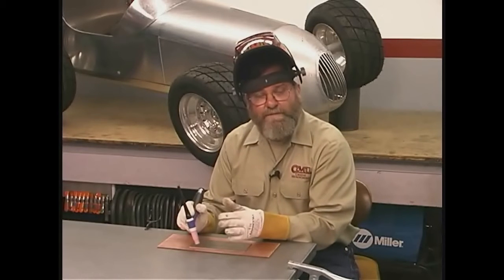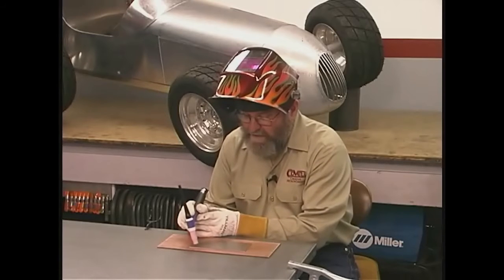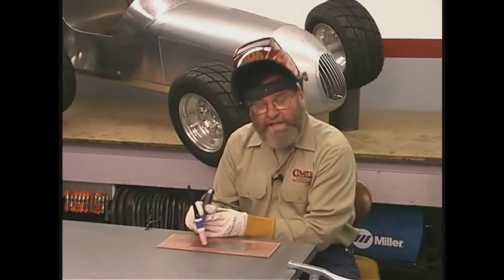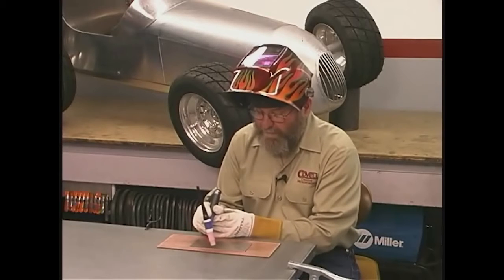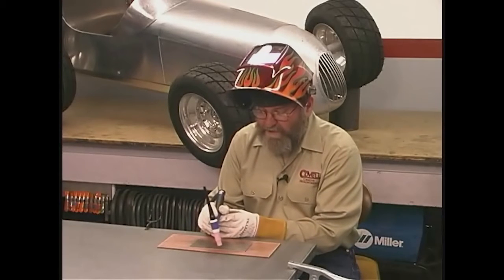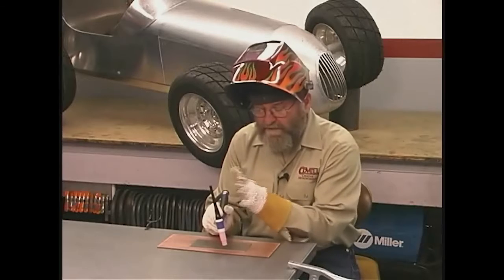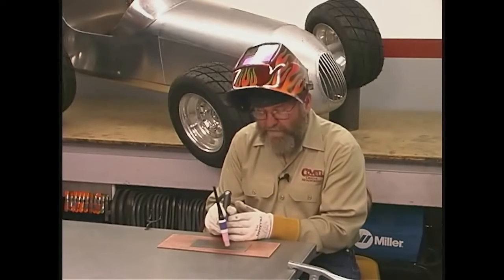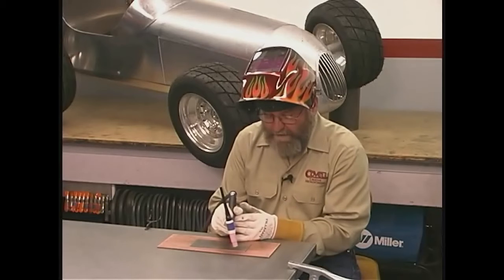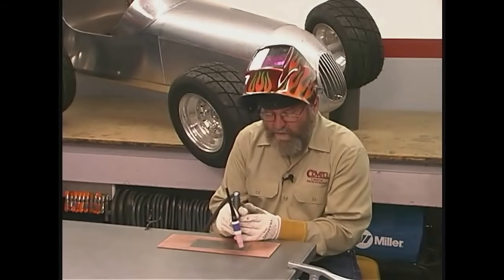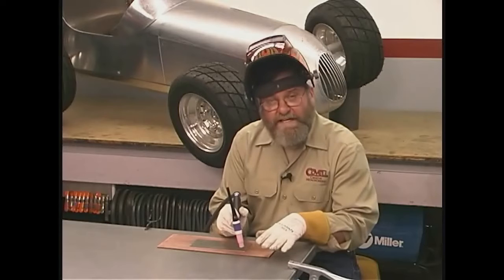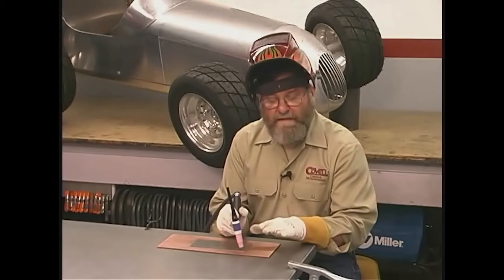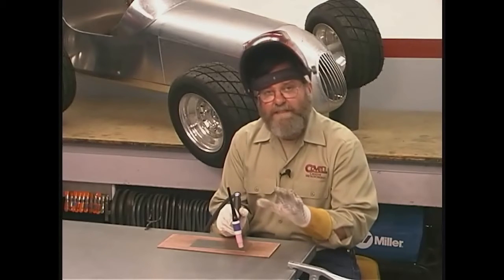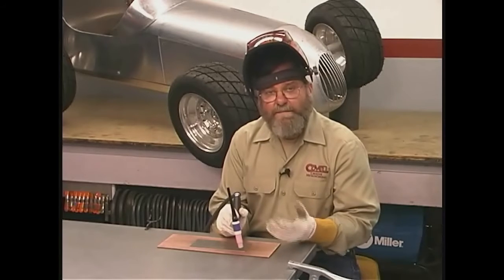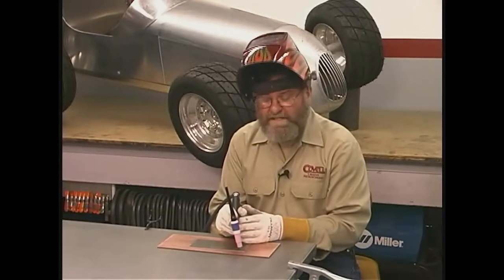Once the puddle is formed to the proper size, then I start moving the torch very slowly toward the other side of the plate. It's very important that I move the torch smoothly and evenly. Very important that I maintain this 10, 15, or 20 degree angle. Once I'm approaching the end of the weld, I stop moving the torch and I start backing off on the foot pedal. Once the foot pedal reaches the top, the arc will stop, but the gas will continue to flow because we have 10 seconds of post flow programmed into the machine.